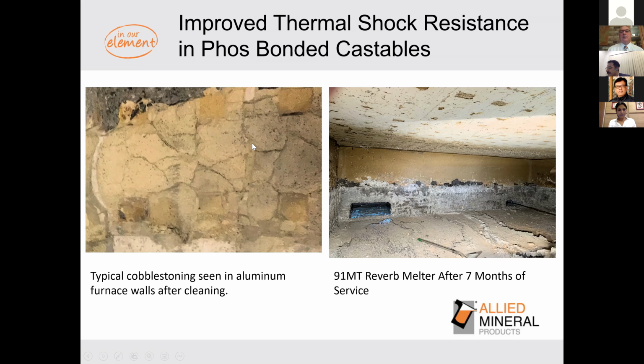So what I really love about this product, again, as you can see in the picture on the right, is a 91 metric ton reverb melter after 7 months of service. I apologize that the picture wasn't zoomed in a little closer, but I think you can see even from that distance, the vertical cold joint that the contractor put in, but there's none of the cobblestoning, because it takes the thermal shock so much better than a cement bonded castable.